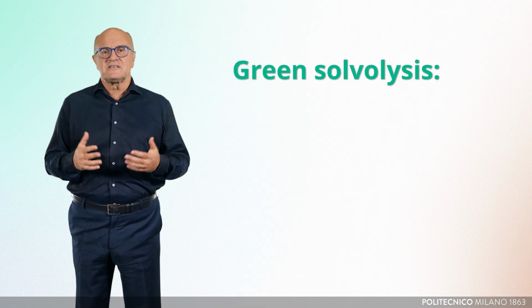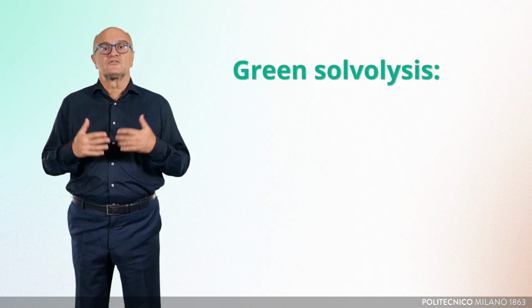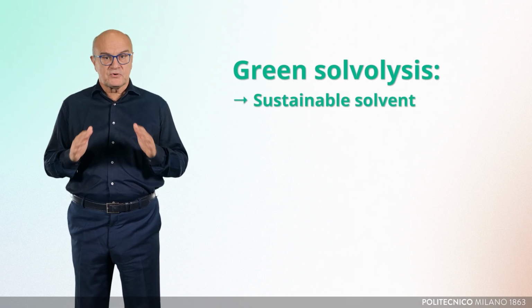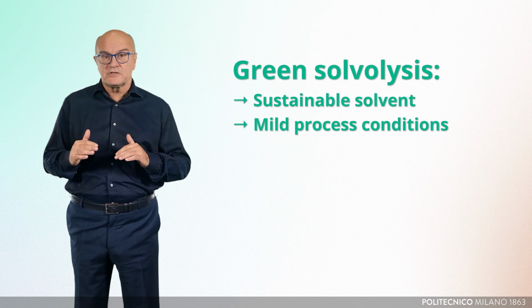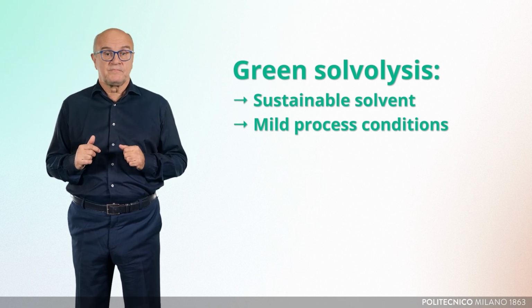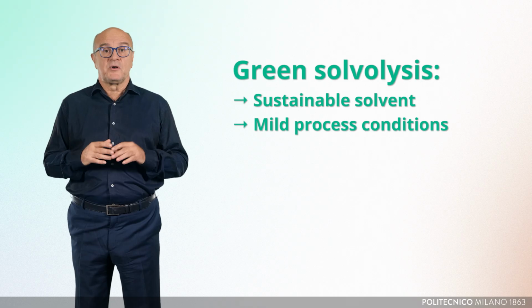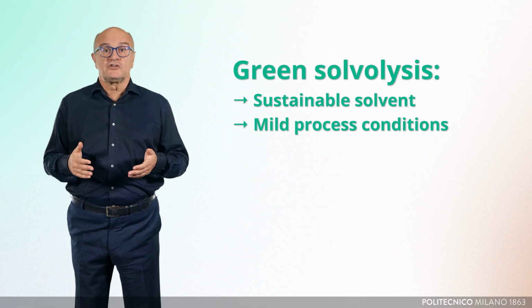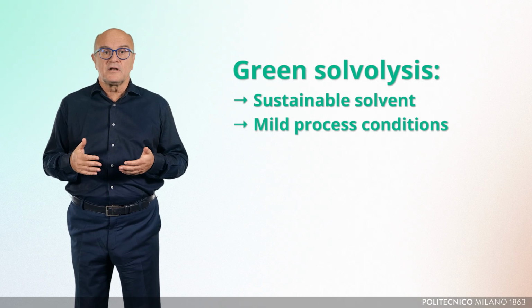Chemical recycling by green solvolysis in mild conditions is an innovative and promising technology that instead not only recovers valuable materials but also aligns completely with the principle of a circular economy. Green solvolysis is a chemical recycling method that uses sustainable solvents and mild process conditions, such as relatively low temperature and atmospheric pressure, to selectively break down the polymer backbone into original monomers or oligomers with a controlled stepwise process.